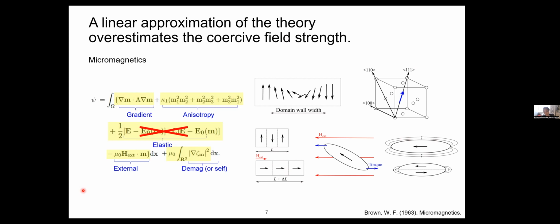So essentially, when you're applying an external field to the magnet to reverse its magnetization, it's an interplay between all of these energy terms, which allows this magnetization to switch from one direction to the other. And so William Fuller Brown, who was also very interested in the Permalloy problem, tried to apply this micromagnetics theory to predict hysteresis, or to understand if we can predict the coercive force for a given material.